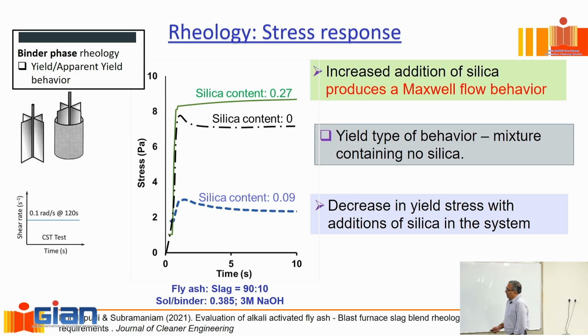Well, we're doing a constant strain rate experiment, and if I take fly ash and slag, now look at the proportion we're using. We're using 90% fly ash, 10% slag. Again, it's an alkali activated material. We are basically combining it with an activating solution which has 3 molar sodium hydroxide. Okay, and the solution to binder ratio is around 0.39, roughly equivalent to a water to cement ratio of 0.4. Now, what we are doing in this experiment is increasing the silica content. So what are we doing? We are actually dosing more and more silica into the solution.